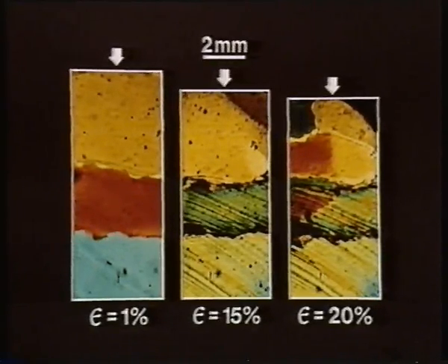The basal plane in the yellow grain is lying in an orientation unfavourable for easy glide. Consequently, it accommodates the superimposed strain by first undergoing lattice bending that ultimately develops into kink bands. Within any aggregate, grains with an orientation similar to the yellow grain are unstable and may be reduced in size through adjustments of the boundary between neighbouring grains. Such grain boundary adjustments are generally prominent in zones of high strain concentrations such as kink bands.